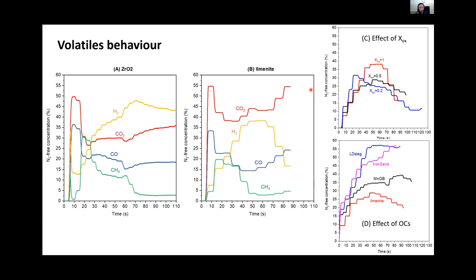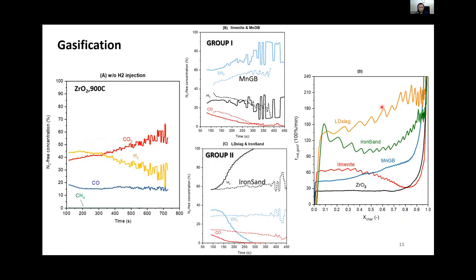Further, we use hydrogen concentration, because it has a difference for these two cases, to compare the effect of oxygen carrier oxidation degree, or XOX, and the OC type. The volatiles conversion is very similar for all the oxygen carriers. We will not discuss more on volatiles, but put special attention on the char gasification. So here come the gasification results.